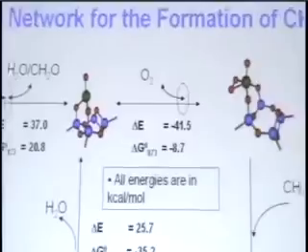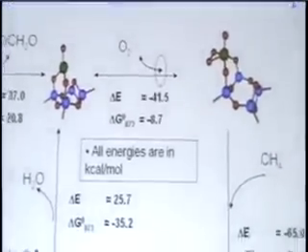So we propose that we have a reversible redox over here. Oxygen will adsorb reversibly to make this peroxyl structure. Methane will interact with that to make a methoxide and a hydroxyl. So we're basically adding methane across this bond here of the dioxyl. And then there's an intramolecular transfer of a hydrogen atom from here to here.